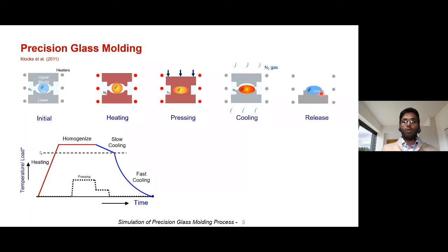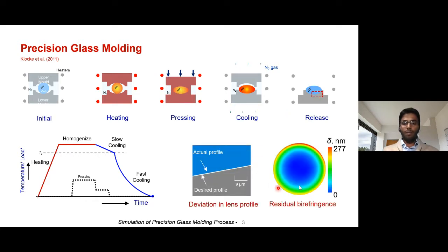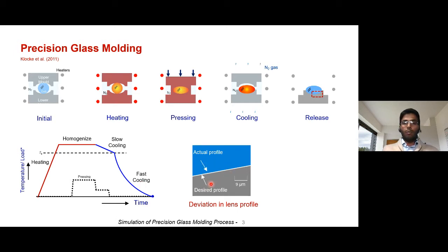And if you take a closer look at the surface of the lens and the surface of the molds, you would see something like this. If you look carefully at the profile of the lens, which is in blue color, and the profile of the mold, which is in grayish color, there is a very small deviation, about 9 micrometers. In an engineering sense, one would say, oh, 9 micrometers is totally fine, it's acceptable. But it is actually not for lens applications, because it has to be precise. We have to keep in mind that it is being used for an optical application, maybe for a microscope, or maybe for CD players where you have micro lenses. So the surface profile has to be as accurate as possible, well below 1 micrometer. This deviation would induce several defects in the lenses, and hence these products cannot be used for the desired application. So the necessary care has to be taken while fabricating the lens.